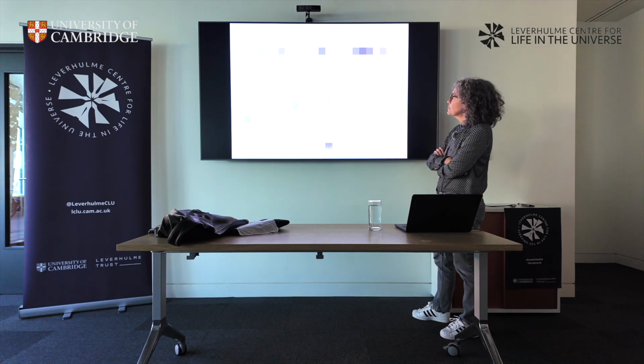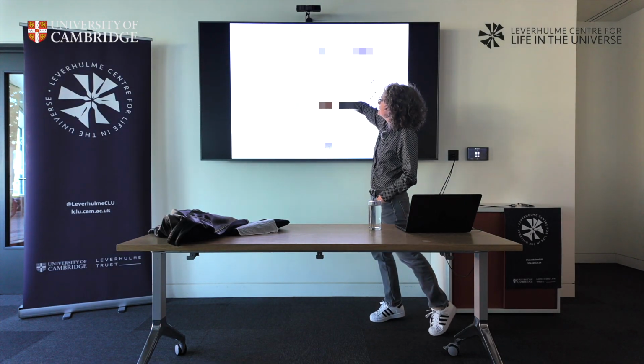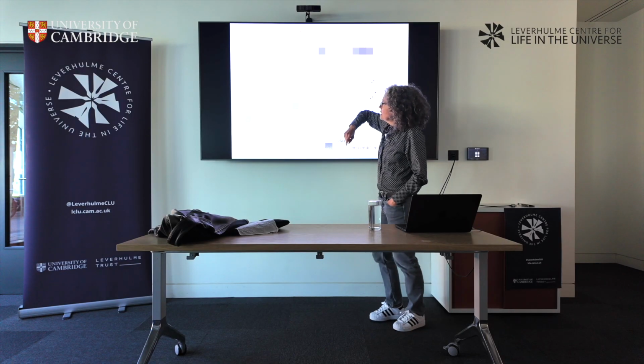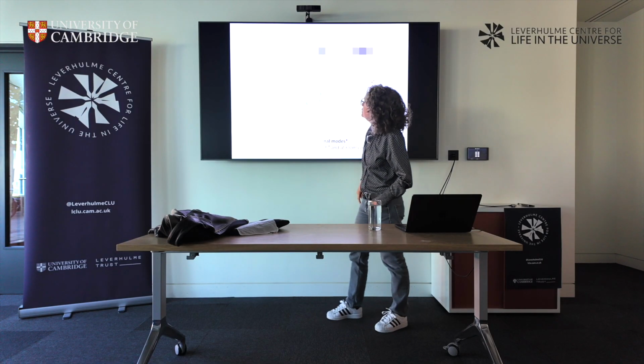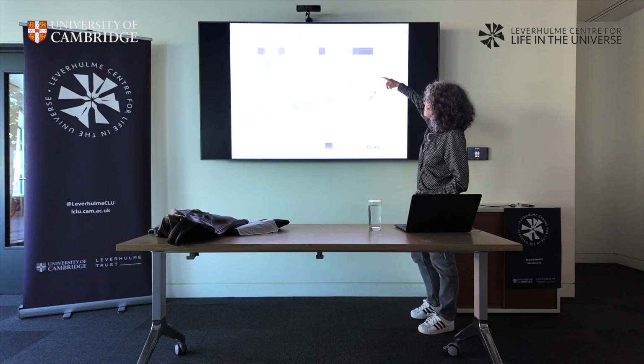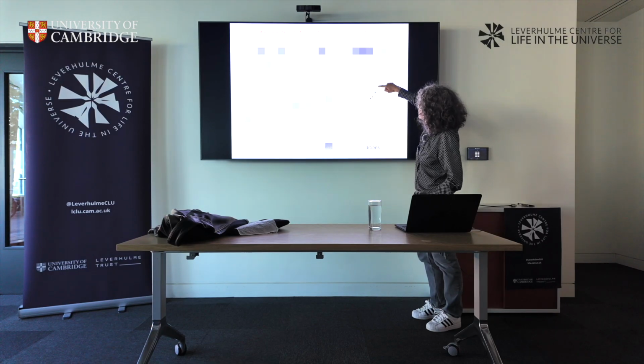And we also have infrared data, infrared spectroscopy, both in situ at high pressure and temperature and ex situ, done at Soleil. Basically, you have the cold sample, then we heat up to 1200, basically 1000 C, and then we recover. So it's very different from xenon. All these peaks here are just normal coesite, but in this zone you have little bumps that become much clearer when you heat up, but I think they are there all the way. You see them better maybe in the freestanding sample. You have these oscillations of peaks that are not there when you don't have argon. All the other peaks are the same, but in this area you clearly have 3 new vibrational modes. They are always there: at high pressure and temperature, and when you quench it.